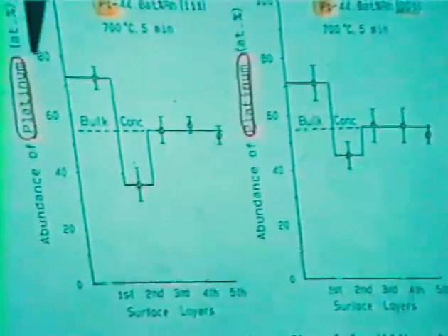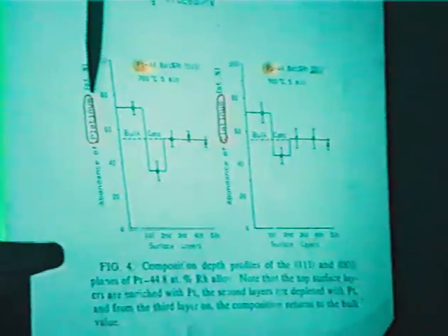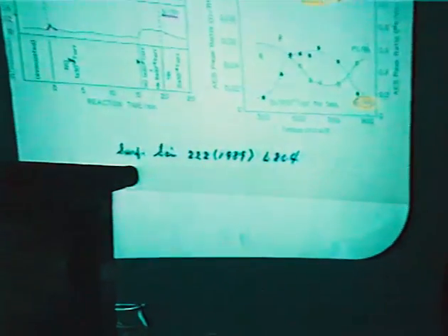And when oxygen comes onto this surface, I will show you the displacement occurs, because oxygen prefers to make a bond with rhodium. So the displacement between the topmost layer and the second layer rhodium occurs during catalysis. I will show you the example. This result was published here.